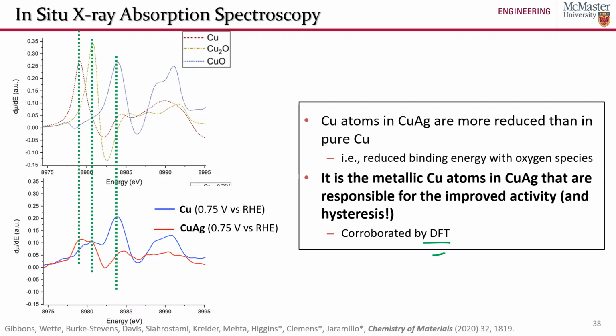And I see the question in the chat: which composition of copper silver was better performing? We found that copper 70 silver 30 was our best performing catalyst thin film, but we found that at most compositions, the copper and silver perform better than just the silver alone. But 70-30 was our best one.